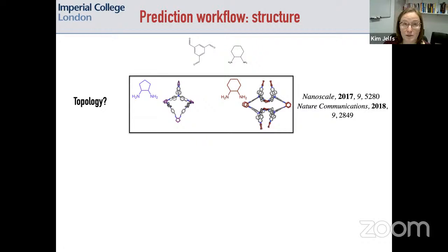So on the left with the purple cyclopentane diamine, that reacts in a 4+6 reaction of 4 of the trialdehydes and 6 of the diamines to form the molecule shown there that is quite porous. It had a porosity BET surface area of about 1,300 meters squared per gram, which at the time when it was made was a record for this class of material. But by contrast, if you just add in one extra CH2 group, as we see on the right-hand side with the maroon-brown cyclohexane diamine, then in that case, you get an 8+12 reaction. So it's double the molecular mass.